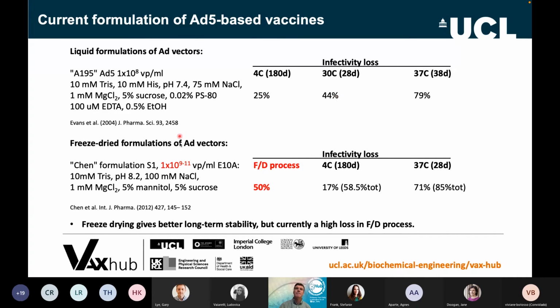So it's usable, certainly when you go to 4 degrees C storage, but less usable as you go to 30 degrees C and upwards. And then the state of the art in freeze-dried formulations, what we call the Chen formulation, essentially had a freeze-drying process where half of the material was lost just getting through the freeze dryer, and then a further 17% stored for 180 days at 4 degrees. So quite considerable loss overall, and then at 37 degrees, again, a total of 85% loss. So there's a lot of room for maneuver, but at least then we had a starting point in terms of formulation to base our work on. So that was the idea.